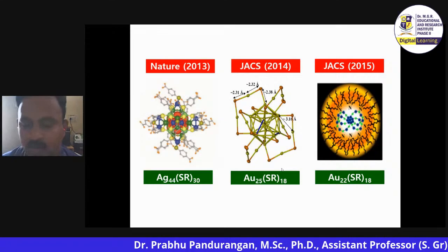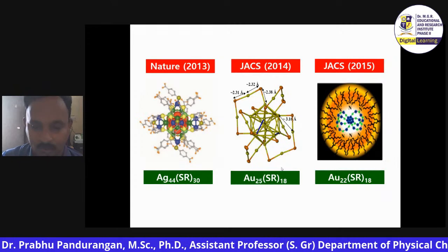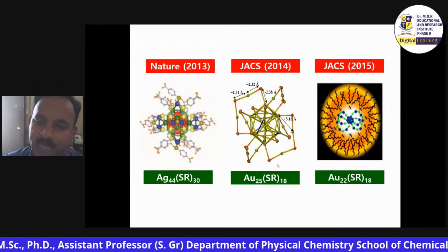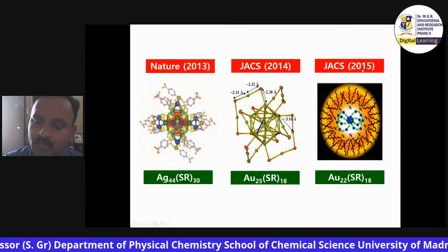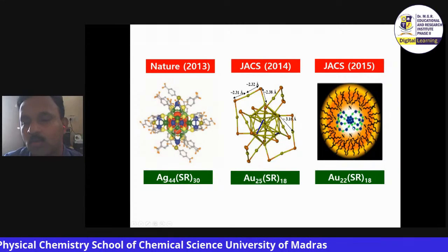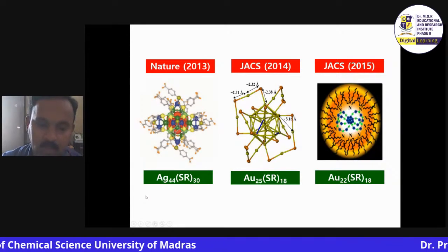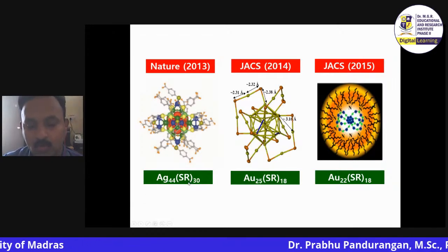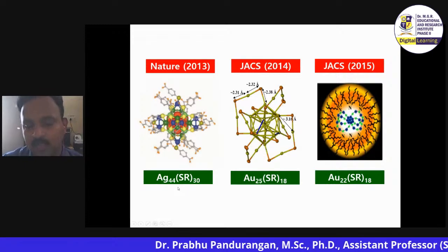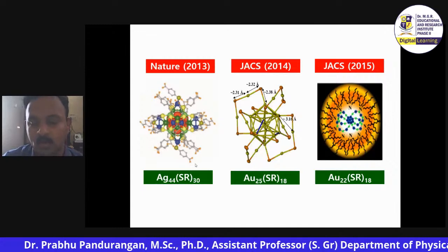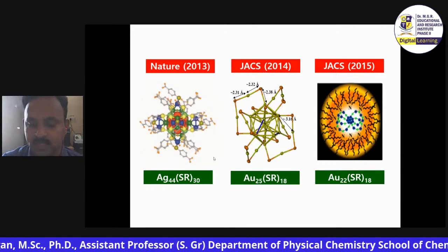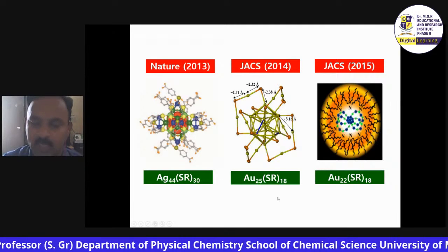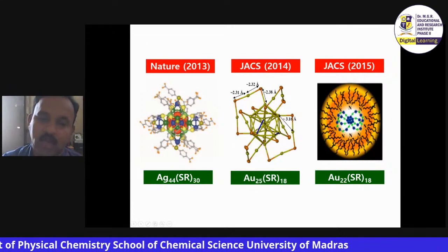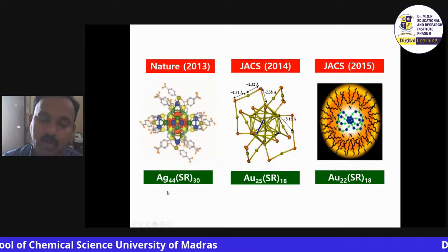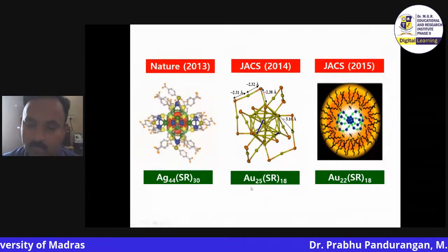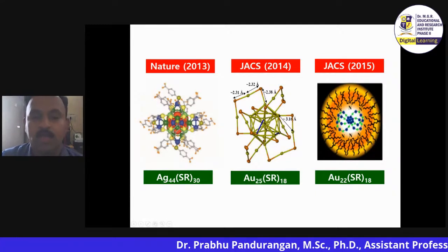This may be an advanced topic for a PG level or a scholarly level, where you can have these three papers which are published in Nature, JACS, and I am one of the authors in JACS 2015 from Yonsei University. I will tell you what contribution I have made in this paper. First of all, you can see silver 44. Silver 44 is about 1.4 nanometer. So far in literature, people have been telling gold is an inert material. Gold is the most stable material. The first stable metal nanoparticle one could say in literature is gold. But to your surprise, in Nature 2013, silver 44 has established superior stability as compared to gold. That is why it has been revolutionary and it is published in Nature.